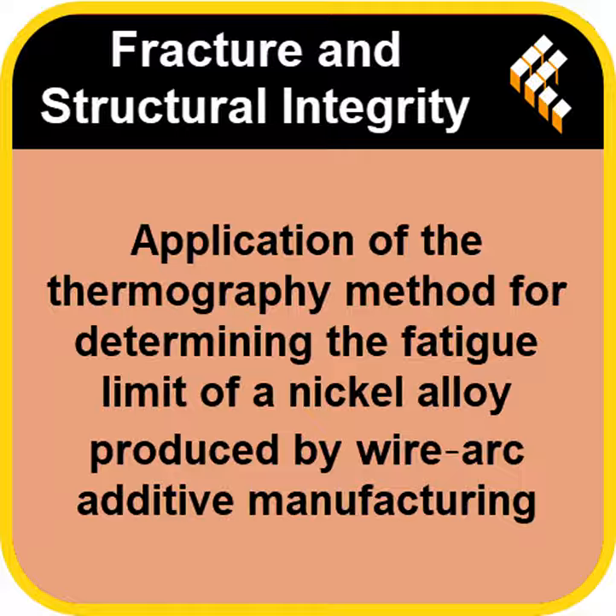Yes, you reset the thermal baseline. That ensures that when you start the next block at a slightly higher stress, you're only measuring the heating effect of that new stress level. You're not getting any cumulative heat buildup. So within each of those short blocks, how did they know when to stop and collect the data?